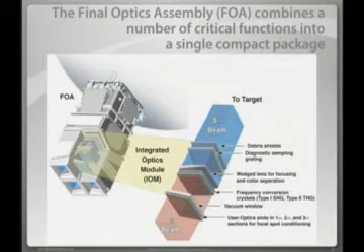We also have debris shields because remember the target, it's small, but when it reaches about 100 million degrees, it doesn't look like a target anymore. It vaporizes, and you get a variety of scales of shrapnel coming off of it, from atomistic, to nanometer, to as large as micron size, but they're moving at high velocities, and they can do a lot of damage to optics. So how we do debris shield technology and the like has also been a very interesting part of the work that has happened here.